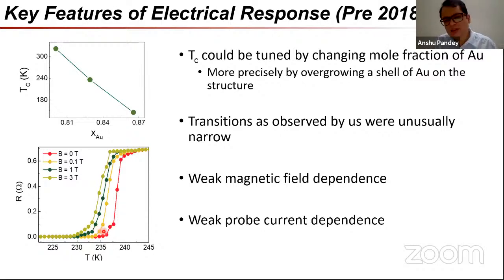So what we found here was that the transitions which we got to a zero resistance state were unusually narrow. These exhibited some magnetic field dependence, but in general a very weak one. And also probe current dependence was extremely, extremely weak. It is something which we were, at least when we were doing the measurements, not able to sample really well. Now, with our collaboration with Professor Arindam Ghosh, we have much cleaner data thanks to him.